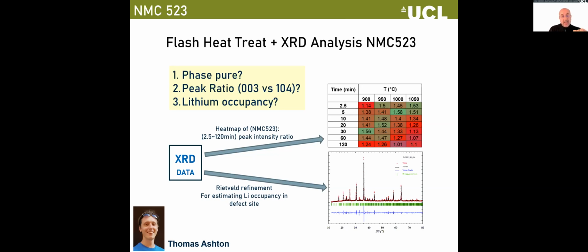And often you'll get a nickel and a lithium swapping places, and that means you've got a defect where a lithium's stuck in a nickel position, or the reverse, where the nickel's stuck in a lithium position between the layers. It's generally considered that if you look at the XRD as a kind of weather vane, these two peak intensities, if they're around about 1.2, and again, this is very much waving in the air, generally if you get a value near 1.2, this is considered to probably give you a good cathode, and you'll get low cation mixing.